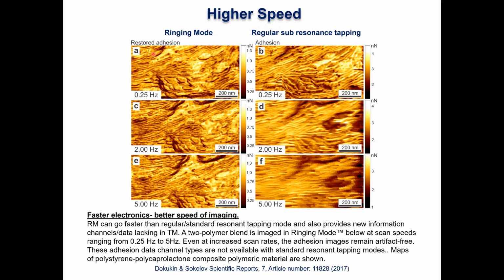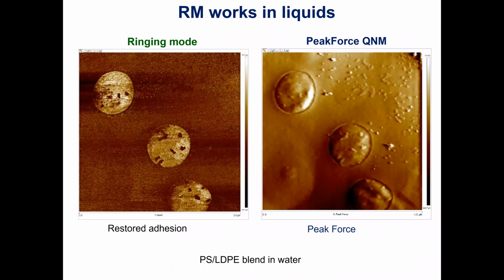Speed, higher speed. For example, if you increase speed, and again, simultaneously record adhesion, and this is restored adhesion, many channels give you a very toleration up to 20 times increase in speed, while you already have kind of loss of resolution substantially in the other modes. We have some reason why. If you're interested, I can definitely answer that question. But this is again simultaneously recorded. No special adjustments or something like that was done.